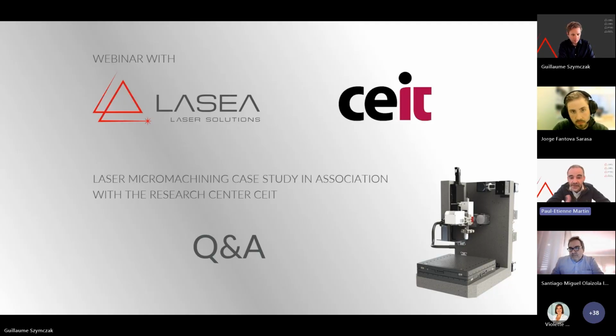on the optical table, and then you will be able to switch in the software from one wavelength to the other. For the UV, we recommend having a separate beam path, so a second station, because three wavelengths beam paths are possible, but they do not withstand a high power, so the lifetime could be reduced. So we recommend using a specific beam path for the UV wavelengths.